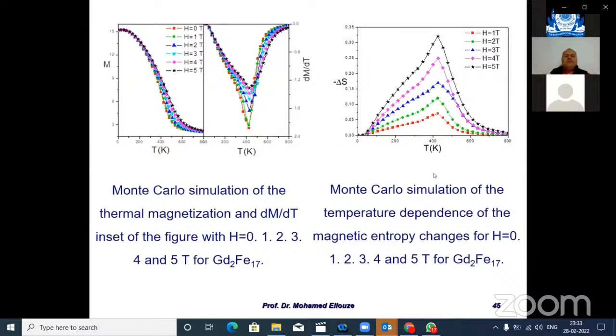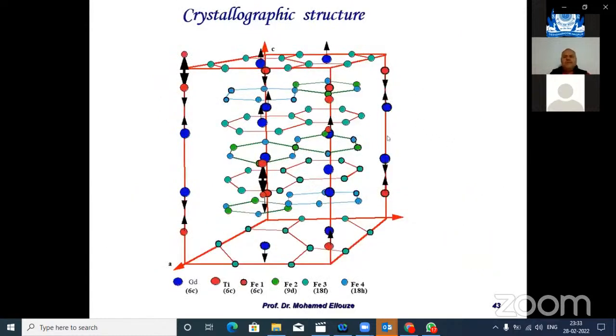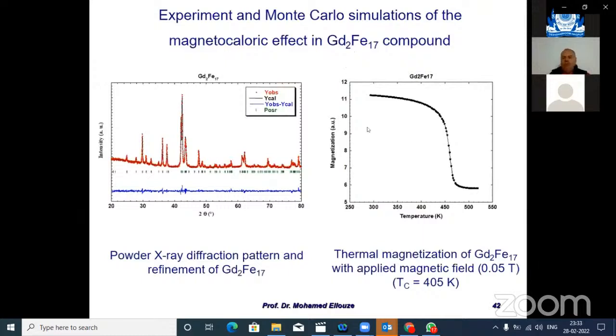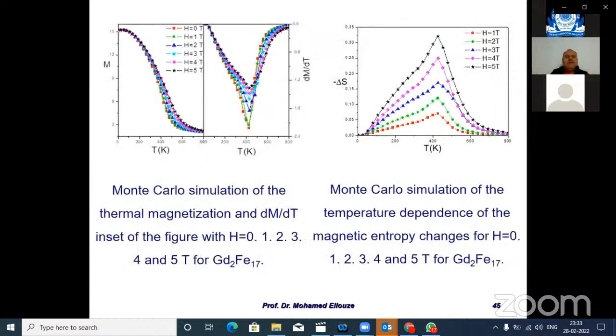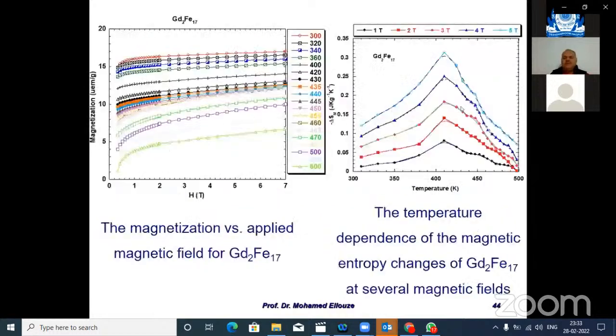Using the Monte Carlo simulation we can also calculate the variation of entropy of our sample, and we can see that we obtain the same variation of magnetization with applied magnetic field for this kind of sample, as well as for the magnetic entropy.